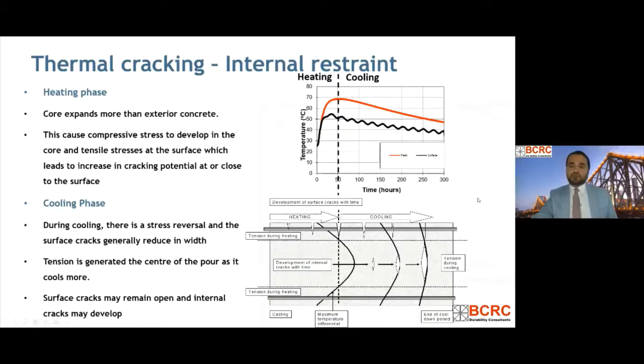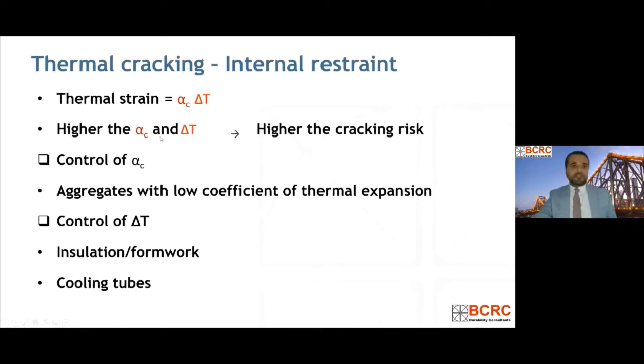Now to evaluate the risk of cracking due to internal restraint, we need to calculate the thermal strains. Thermal strain is calculated with a simple equation: you multiply the coefficient of thermal expansion of concrete by the temperature differential you're getting. So it depends on two factors. You can see from the equation, the higher the coefficient of thermal expansion and the higher the temperature differential, the higher the cracking risk.